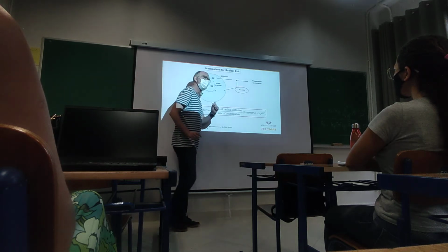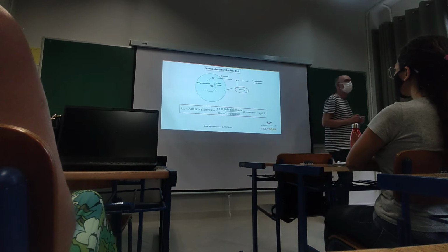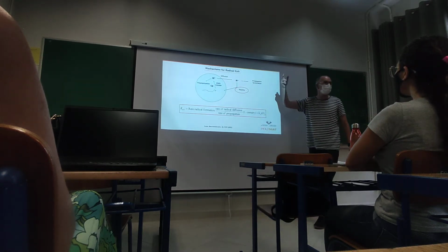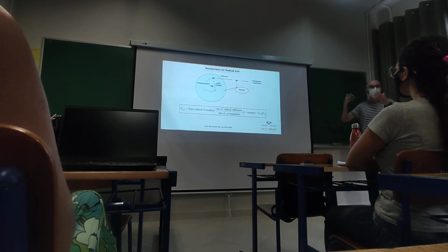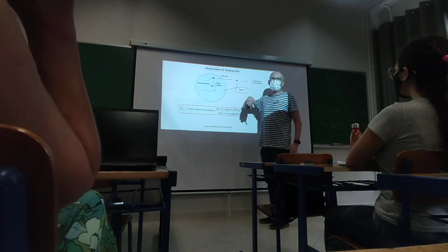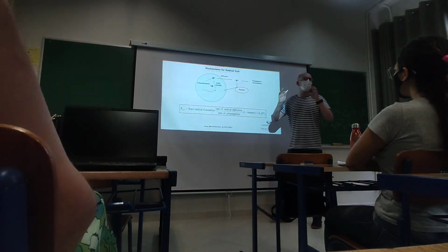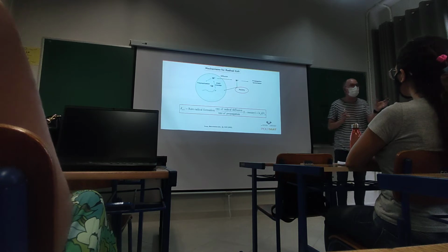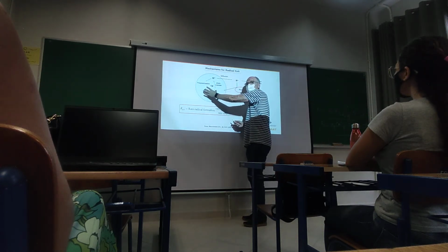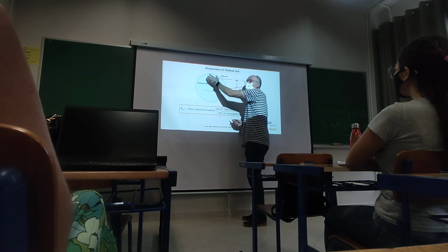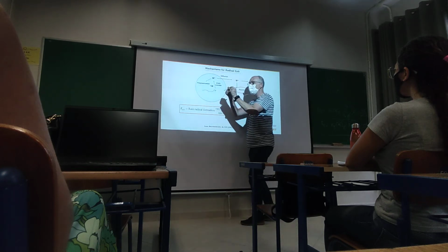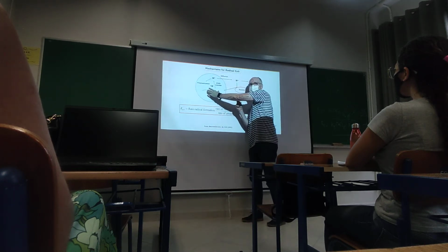Okay, now the other mechanism that controls the average number of radicals of the particle, which is the exit or the desorption. You will see also in some papers desorption of radicals. So, desorption or exit of radicals occurs only for certain radicals. Not all the radicals can exit. In the polymer particle, we will have growing radicals with different sizes. Not all exit. Why? Because the polymer radical here will be sufficiently long.